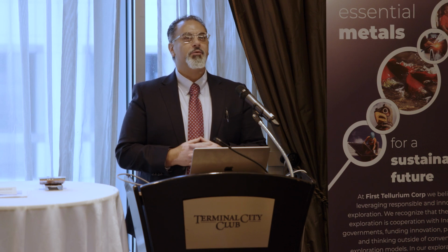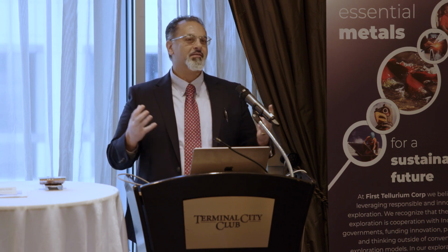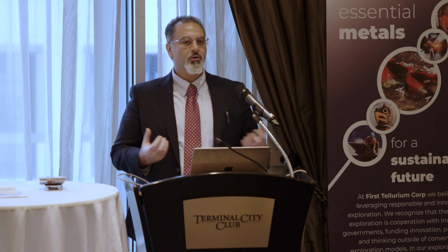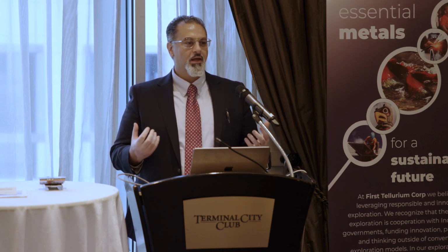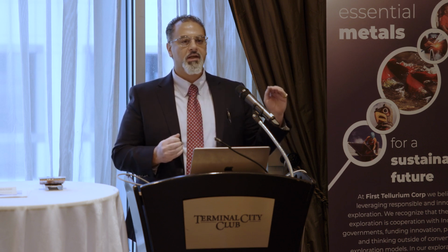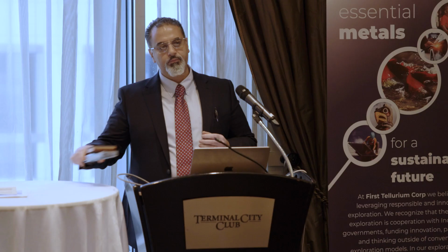So some of you may be familiar with thermoelectric devices. They've been around for a very long time. None of them is suited for long-term commercial application that can withstand high heat. Because I don't have any solder here, this device can withstand 600 centigrade. So this can take the exhaust from your car and will generate electricity if there is a heat differential without any components failing. I tested it for a very long time.